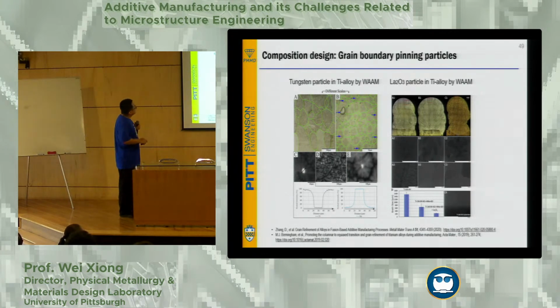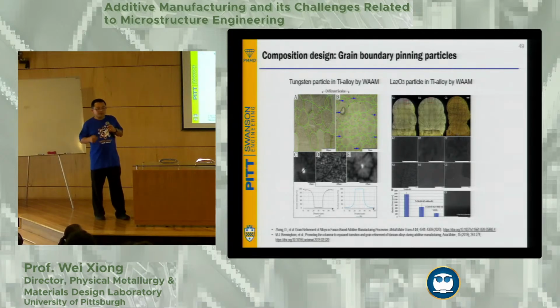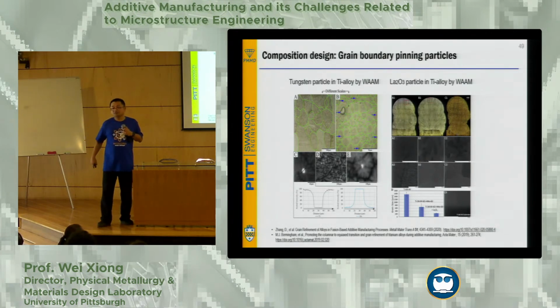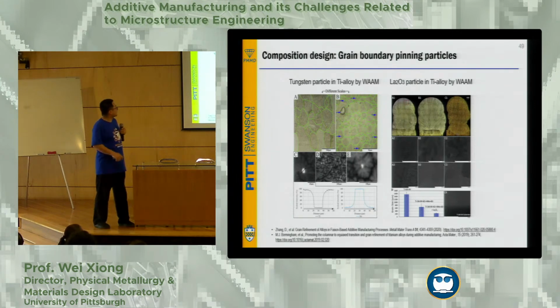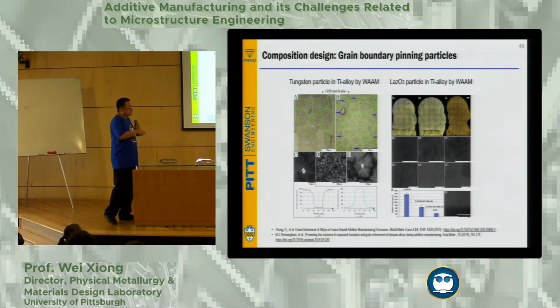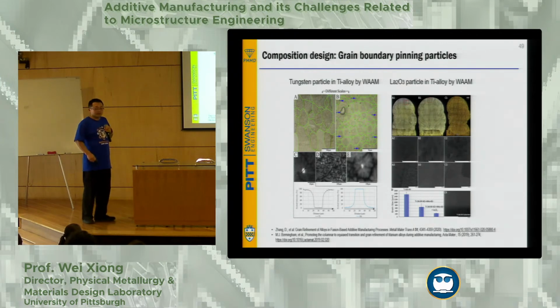As you can see, this is a kind of titanium alloy printed by wire-arc additive manufacturing. It's the same as we printed with the Haynes 282, a wire welding process. The grain size is very big. They were using the same concept as inoculant particles, putting some tungsten particle into the material, because tungsten is very hard to melt. So therefore they act as an inoculant particle and refine the grains. Particularly if you do the heat treatment, because tungsten particle is also resistant to coarsening, they can maintain the small size of the particles.